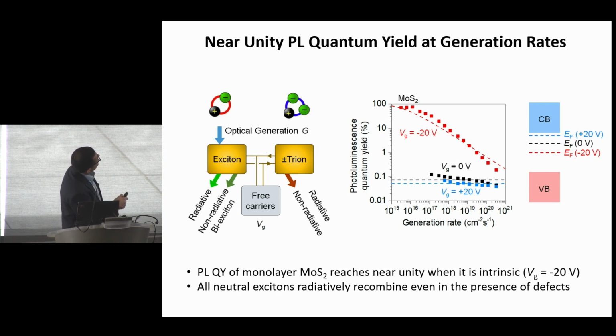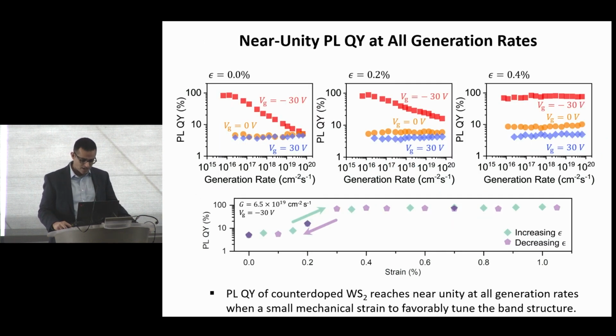And the way you can control the concentration of the two is by doping. If your semiconductor is intrinsic, the Fermi level is close to the mid-gap, you mostly have neutral excitons. If you are doped, either electron doped or hole doped, you have a large background charge, then you can form trions. So the gate is modulating the exciton to trion concentration ratio.